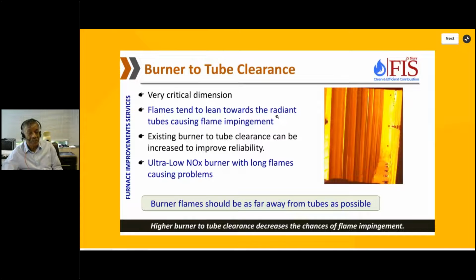What has happened in the industry is that in the last 20-25 years, we have started resorting to low NOx burners, and low NOx burners, as you know, have a very long flame length, almost 2 to 2.5 times the flame length, and that increases the chances of flame impingement. So if you can keep your flames away from the tubes, that will be the best. And as I said in the beginning, since it's such a high temperature furnace, once it starts running, you cannot see any flame because the bridge wall temperature or the firebox temperature is more than 2000 degrees F. So it's virtually impossible to see the flame. You can only see it during startup or when it is running cold.